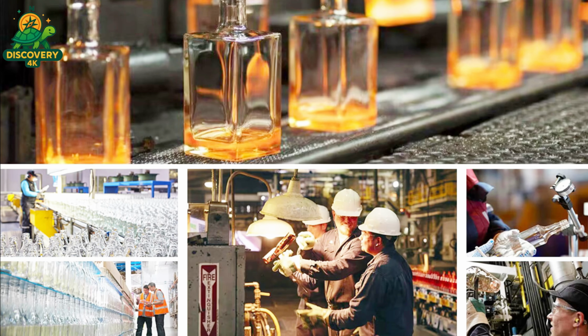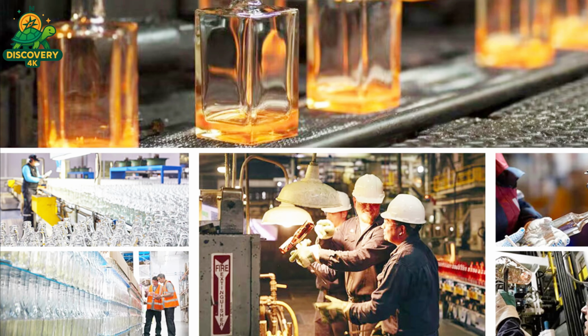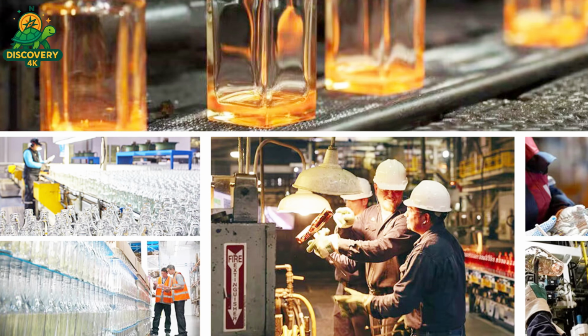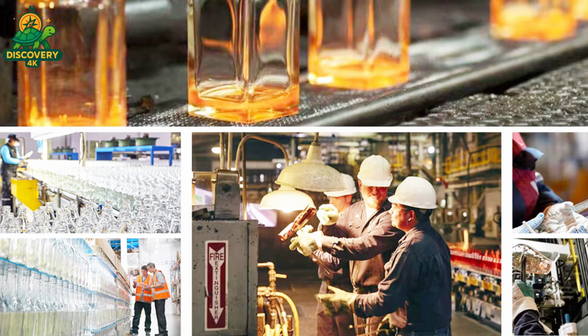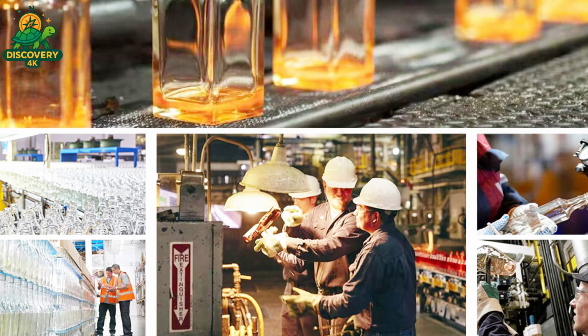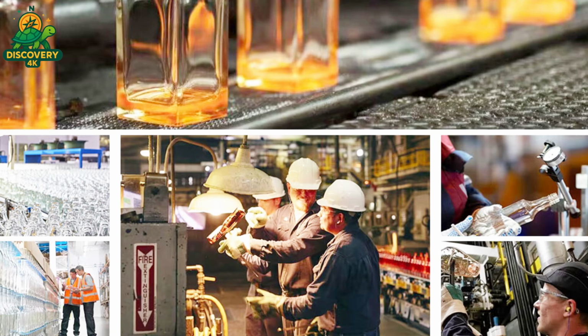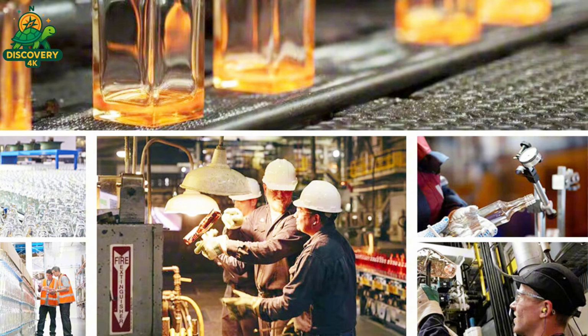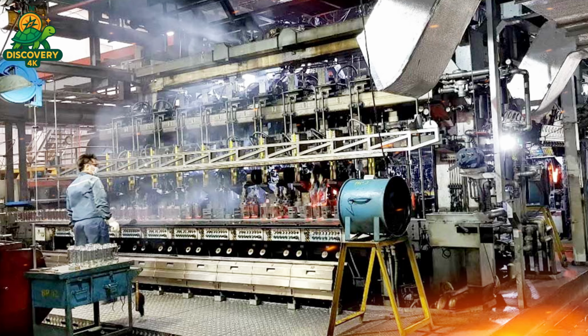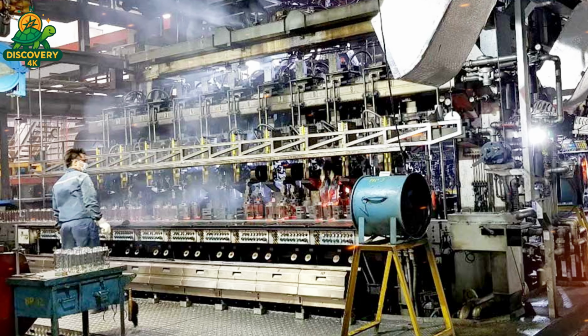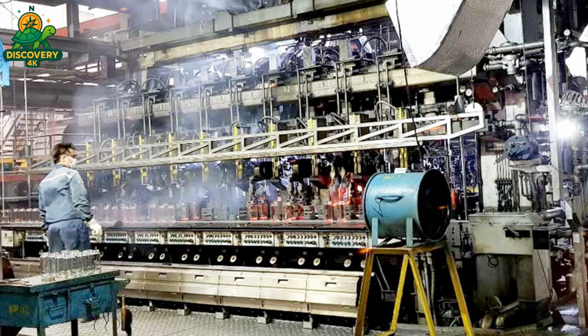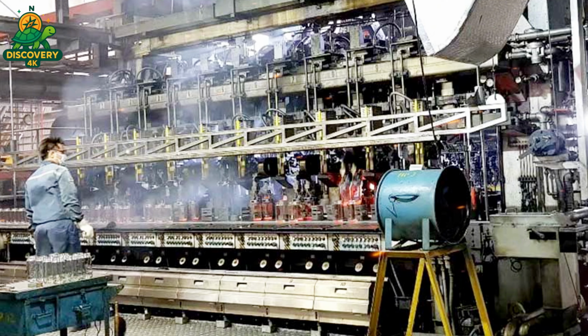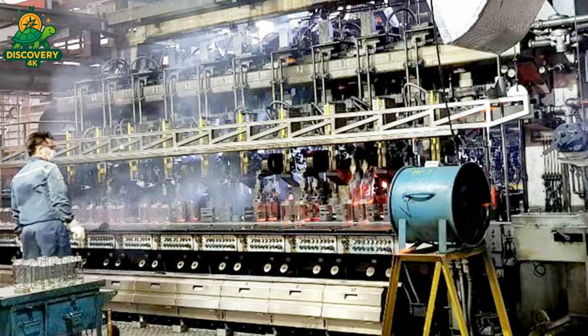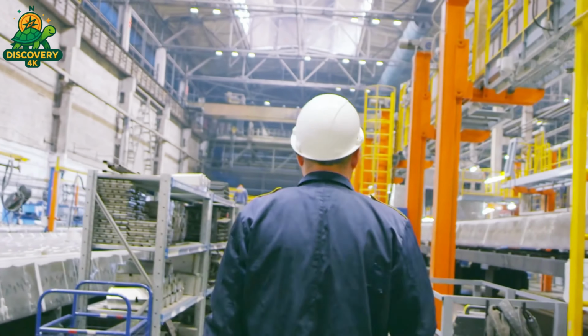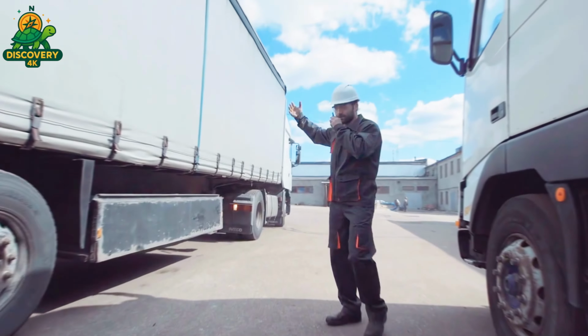Specialized machines measure every part of the bottle: neck diameter, thread alignment, wall thickness, bottle height, and symmetry. For certain uses, like pharmaceuticals or pressurized beverages, tolerances are razor thin. Select batches undergo pressure testing, where water is pumped in until the bottle bursts, ensuring it meets minimum burst resistance. Others are subjected to thermal shock tests, where bottles are rapidly heated and cooled to mimic real-world conditions.